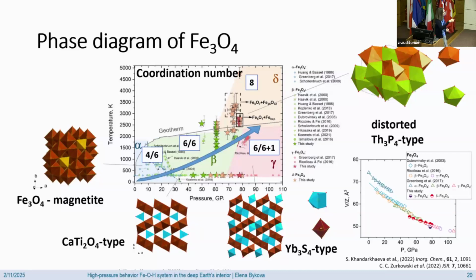And if you go a little bit higher in pressures and temperatures, you start stabilizing some distorted polyhedrons with a higher coordination number equal to 8. All of that is done in order to optimize the positions of atoms in the crystal structure to make the structure denser as a response to the high pressure. So you see how the volume of the compound just decreases drastically if you change the coordination number here. It just drops here and further away.